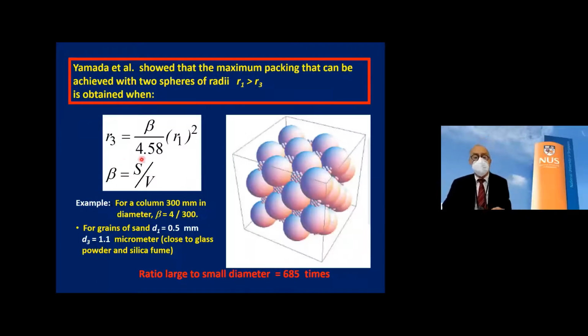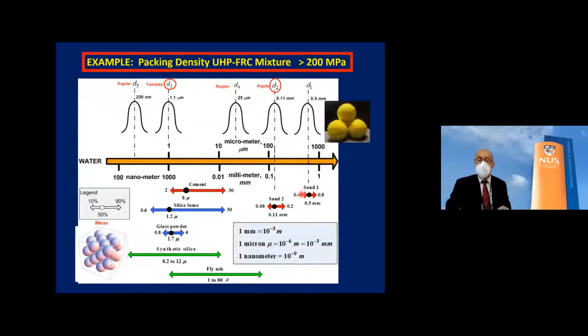Okay, so I took this, calculated, for an example, taking a column of 300 millimeter, I took the diameter of the big sphere here, 0.5 millimeter, and I got D3 1.1 micron. Very small, but by using this, I might be able to increase the packing density to 80%. Okay. So now this is typically what we selected for our mixture.